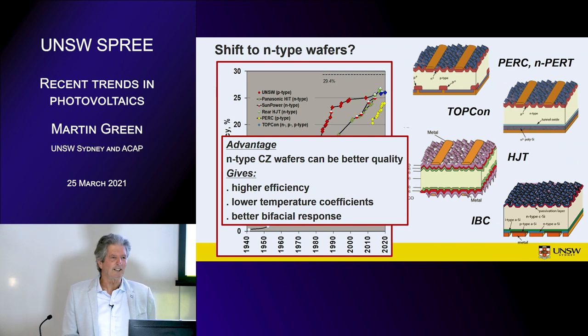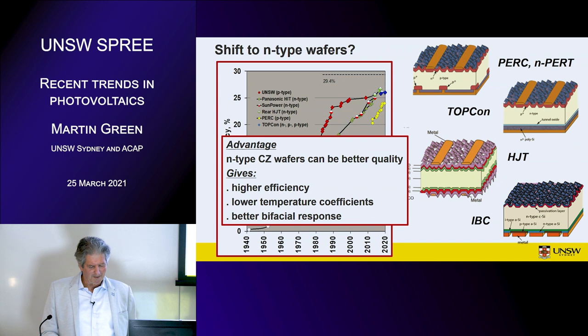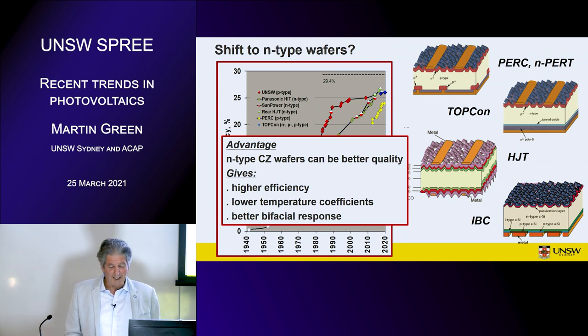So the only way you can get the efficiency advantage is through voltage. So to get the voltage, you need to have really good material. So it really puts new pressure on the quality of the N-type wafers. But if you have a good N-type wafer, you can get good voltages, and that gives you a higher efficiency. You can get a lower temperature coefficient. The closer the open circuit voltage is to the band gap, the lower the temperature coefficient. And you get good bifaciality because you need this good material, so it's going to be able to collect carriers right across its thickness.